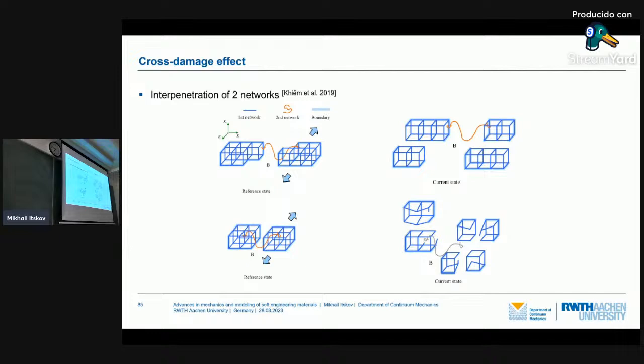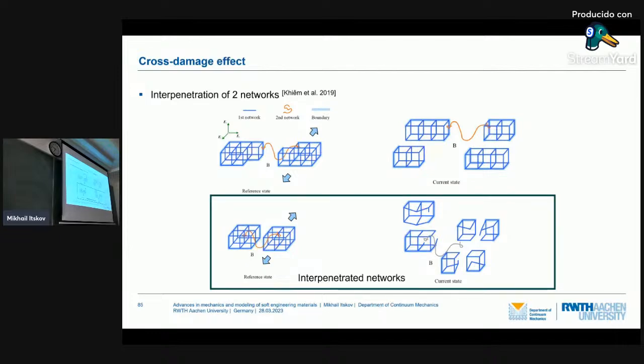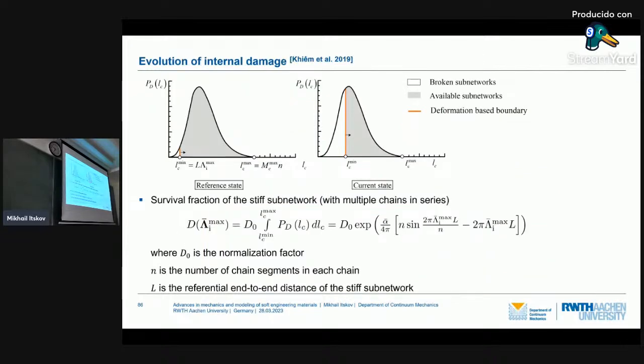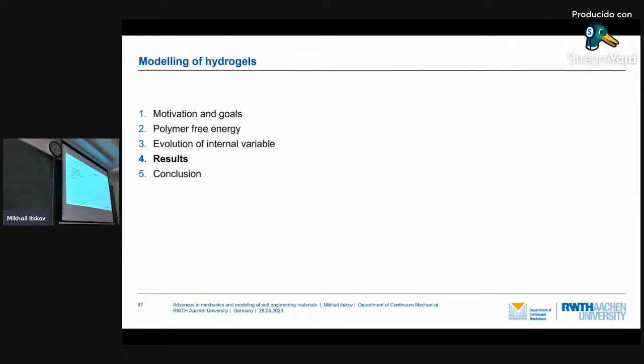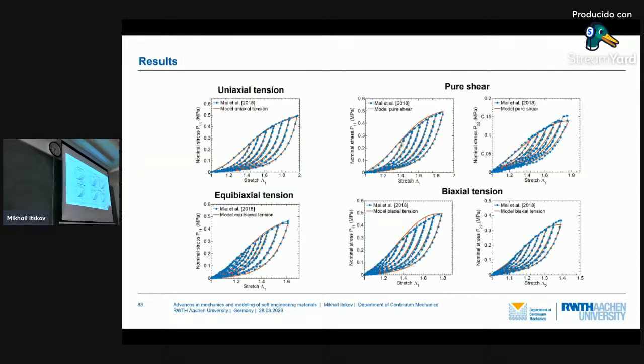And this is what we try to take into account. You see here that parts of this first network are also destroyed under tension, and using the same idea, integrating over this gray area the number of active chains, we can obtain the number of active chains in this direction, and then take it into account in this analytical energy concept. You see here the comparison to experimental data, rather good agreement under uniaxial tension, equibiaxial tension,